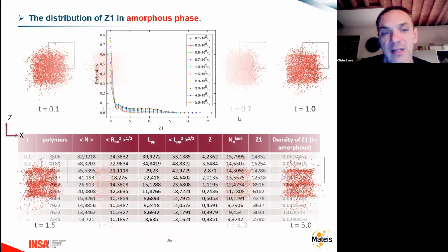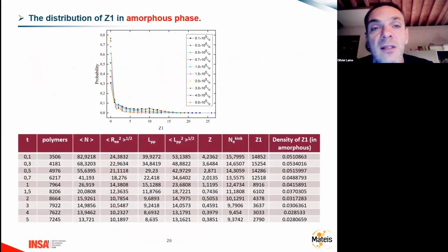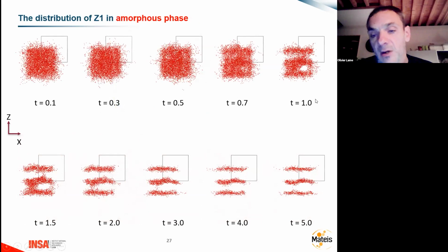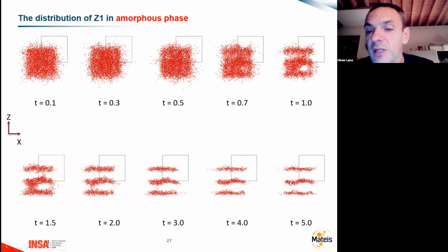So in fact, we perform again the same procedure, but only in the amorphous phase. And then we see that there is here a little peak, which gives the probability to find a chain with only 3 or 4 entanglements. And then there is a much higher probability to find chains without any entanglement, which is quite logical given what we said before, because we have a lot of very small chains in the amorphous phase which can disentangle. And so the density of entanglement in the amorphous phase is decreasing with the crystallization. Okay, and now we have these entanglements which are localized in the amorphous phase, which is quite logical.